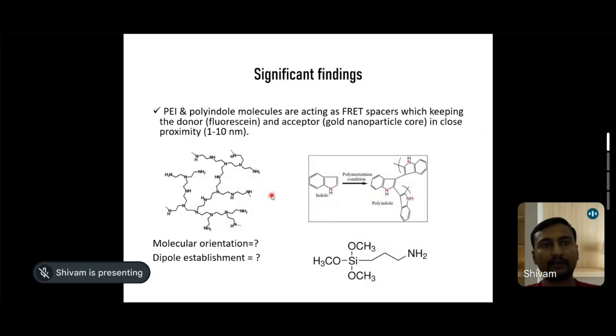So what was the significant finding? Polyethylenimine and polyindole molecules acted as an excellent spacer, which keeps the donor fluorescein and acceptor gold nanoparticle core in close proximity. But still, there is a chance to further study the molecular orientation of fluorescein and gold nanoparticle, and the conditions at which the dipole is established between the fluorescein and gold nanoparticle, except the zeta potential and size of the nanoparticles.